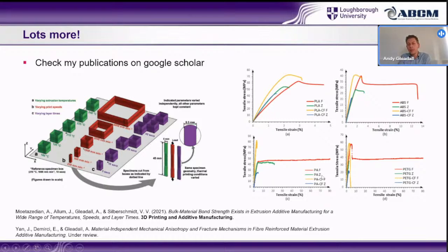Then on the right, this is my student that followed on from the one on the left and was really interested in carbon fiber and fiber reinforced polymers. So here, again, because we've got these quick and easy to analyze specimens, they were able to do loads and loads of tests. So here I'm showing 4 different materials with and without carbon fiber in 2 different directions, the principal worst and best directions, directly along the filaments and directly normal to them in the Z direction. So these are 4 results. They also tested these for all different temperatures and all different extrusion widths and layer heights and all sorts,